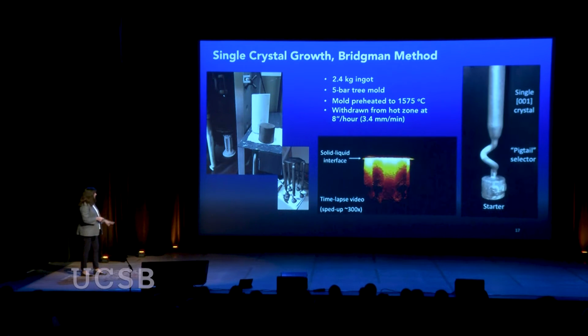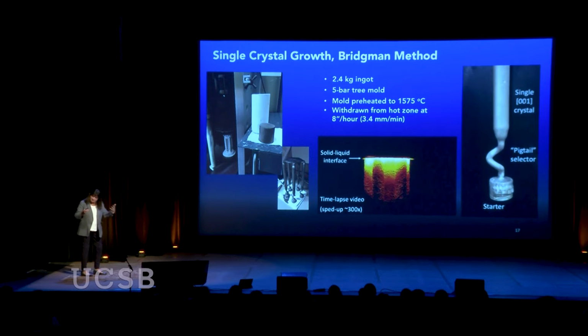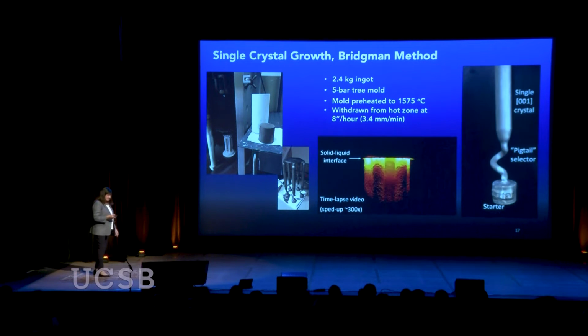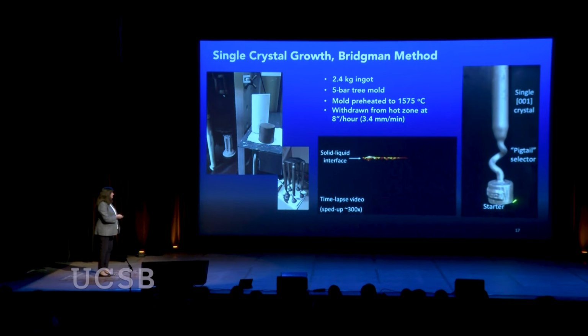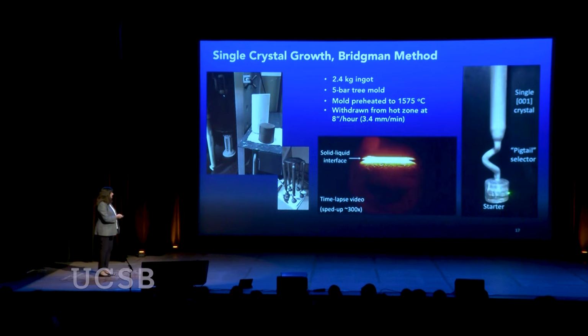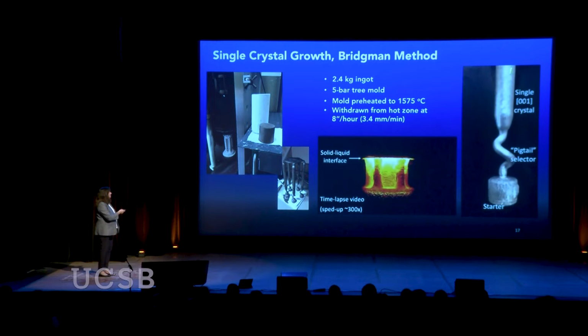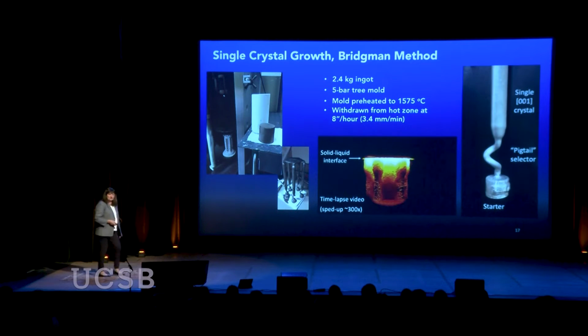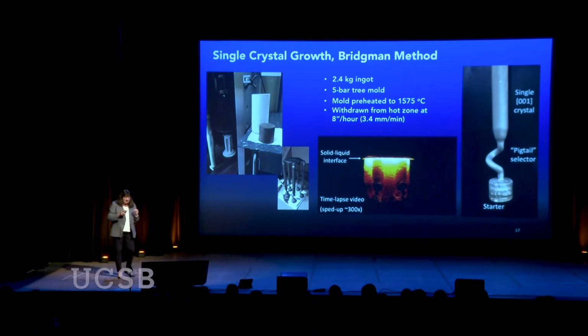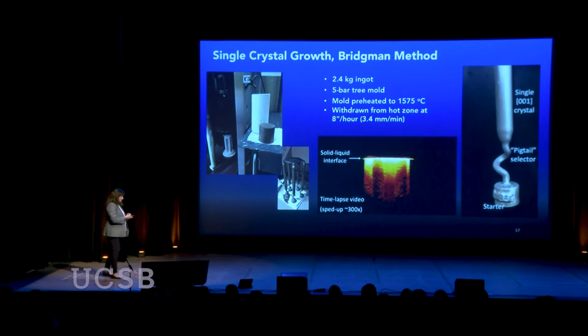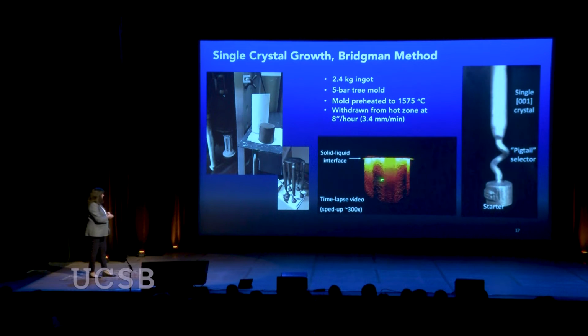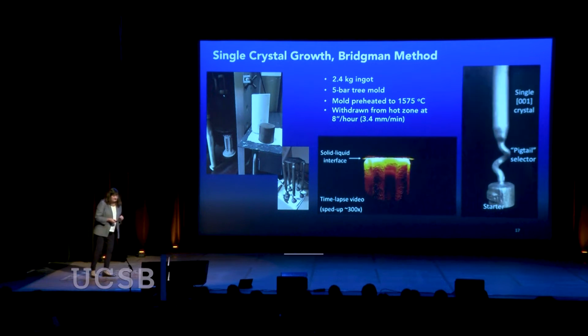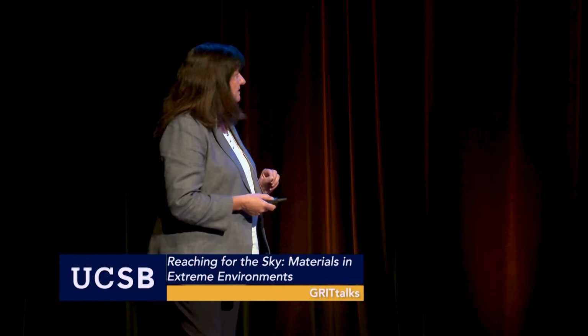And so here we're not growing blades because we're trying to do research and make test specimens. But you can see some of the tricks are in the beginning. You get a bunch of polycrystals down here, and then you force them to grow in ways such that you only have one emerging at the top. And so there's lots of details about controlling the thermal conditions here to arrive at this series of events.